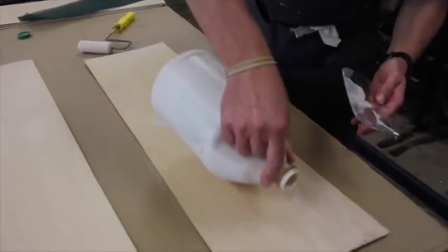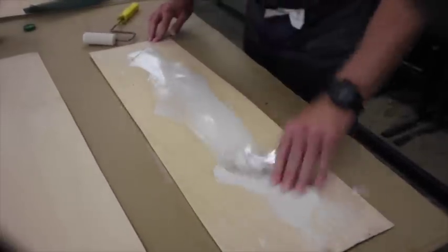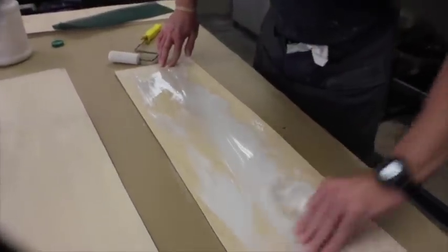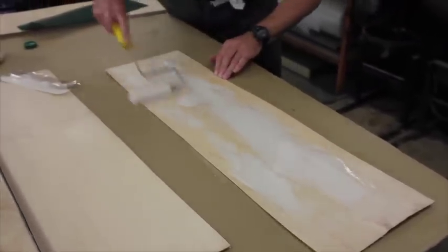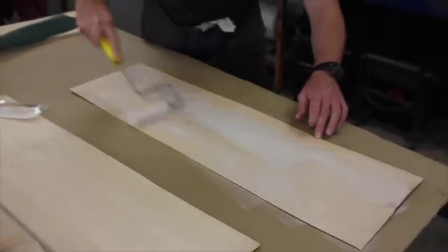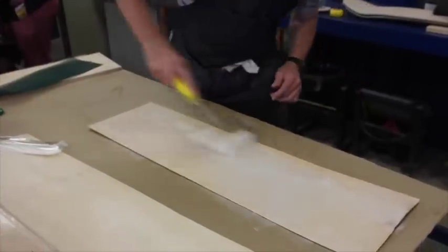Next layer - this one will be double-sided. What's your time limit on drawing time? You want to have it in the bag within 10 to 12 minutes. Is this a two-student job? No. You can, if you get two kids that work well together, absolutely. You can have up to 20 minutes of bag time, but I wouldn't want to push it because the glue's already starting to do its thing.